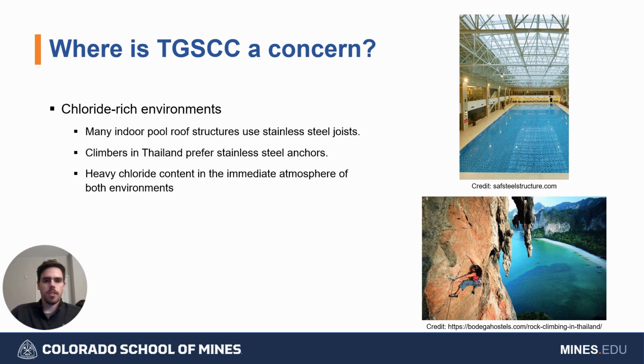As you might expect, TGSCC is a concern in chloride-rich environments, specifically where stainless steel components are used. Many indoor pools, for example, incorporate stainless steel joists into their roofing structures, and because of the high chloride content from the pool water, those joists are prime candidates for TGSCC. Similarly, in the case of climbing anchors, we see TGSCC affecting those, particularly off the coast of Thailand, where climbers often go because of the unique topography. There are very high chloride concentrations in the air around the ocean as well.